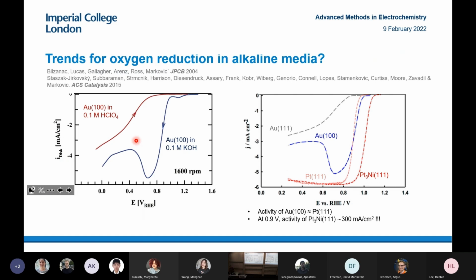However, when we actually look at the data, we see quite big differences between acid and alkaline. So this is on gold 100. In acid media, gold 100 is really inactive. There's a very large overpotential. In alkaline media, it's a lot more active. Conversely, if you look at some other surfaces, gold is a lot more active in alkaline media and less active in acid. And if you look at platinum 3 nickel as well, I already mentioned this very active surface in acid, and alkaline is even more active. There's an unprecedentedly high activity you see for platinum 3 nickel in alkaline media.